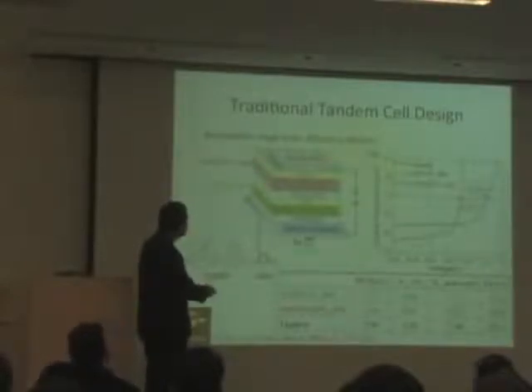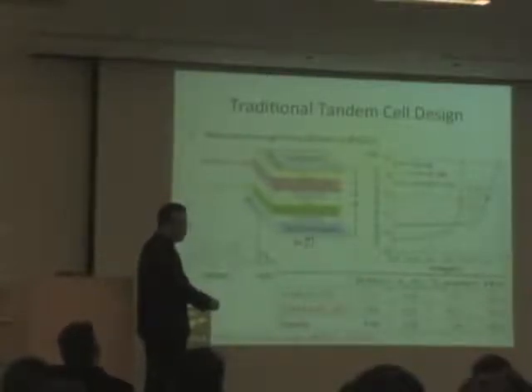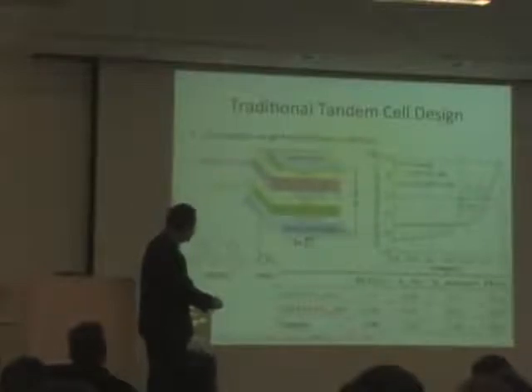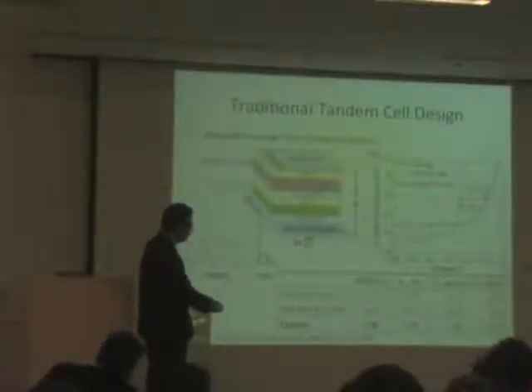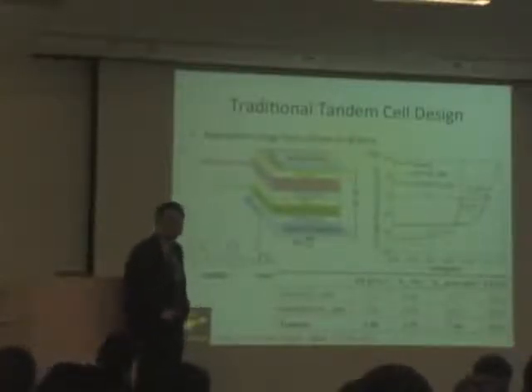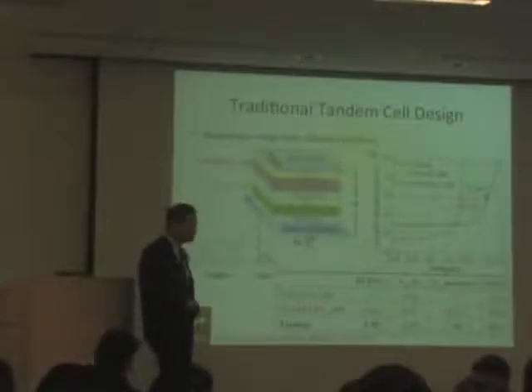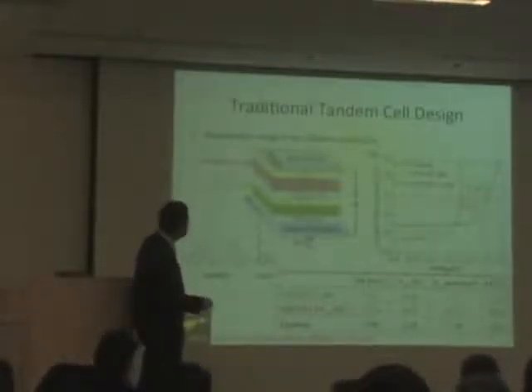This paper was published in 2010. We got 5.9% efficiency. So I want to show you this VOC. If you add these two numbers, you get 1.27, but we get 1.25. We are very close to the theoretical number, so it indicates we really did a good job here. But if you look at the JSC, the black curve is still much lower than where the green curve is supposed to be.